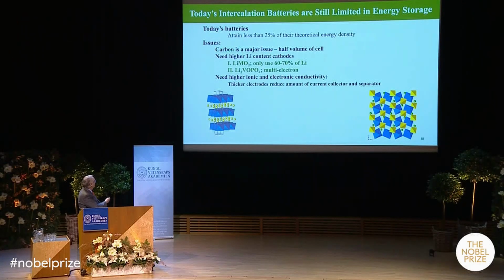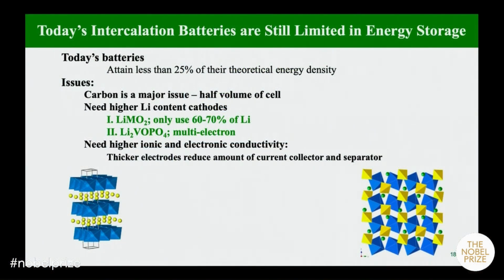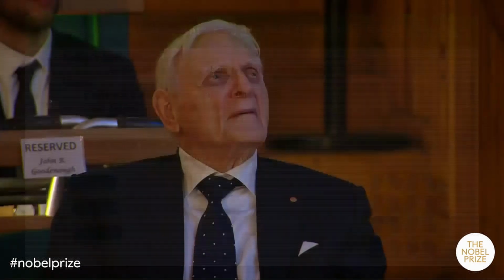One area where there's a lot of work now is to modify the carbon, because the carbon takes up half the volume of the cell. So we want to modify that. We need to get higher lithium contents, because right now the layered oxides, like lithium cobalt oxide, we only use 60 to 70% of the lithium. And then the big issue is, instead of just having 1 lithium per metal, can we push that to 2 lithium per metal?